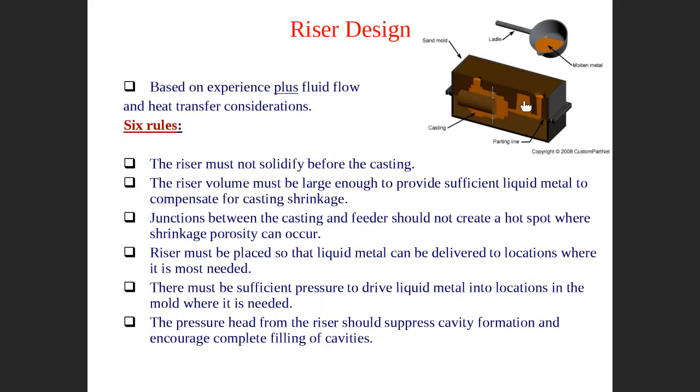I remind you about the riser. The riser is a liquid reservoir. When you pour liquid here, the liquid will fill the whole cavity and the riser as well. I told you before, the riser must maintain liquid for longer after the main cavity has frozen. The main cavity solidifies earlier, and later the riser should solidify. Please listen carefully: the solidification time of the riser must be longer than the solidification time of the main part. Otherwise, it has no meaning.